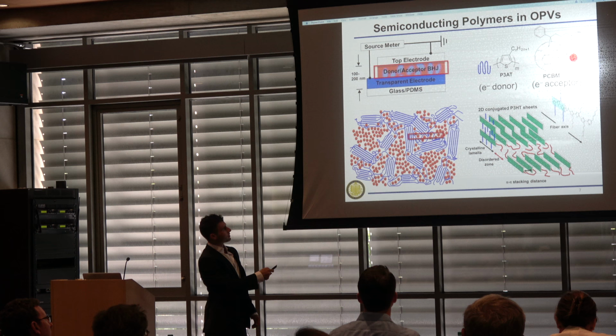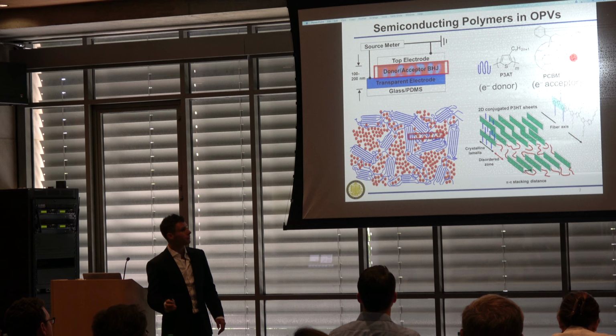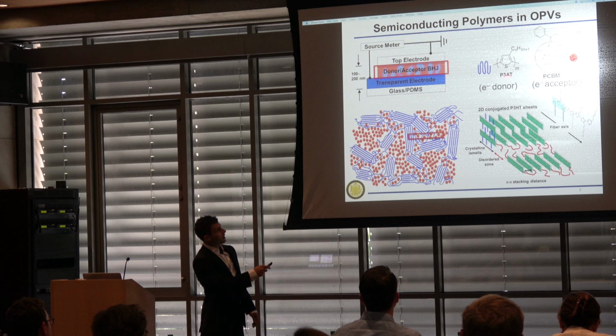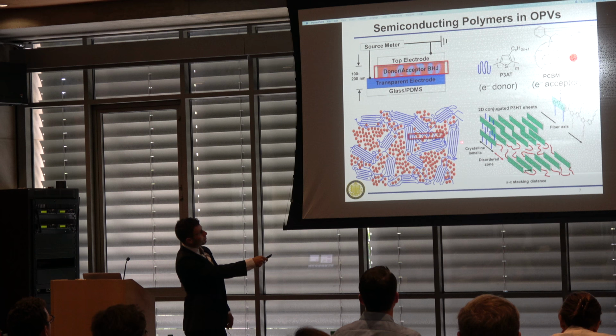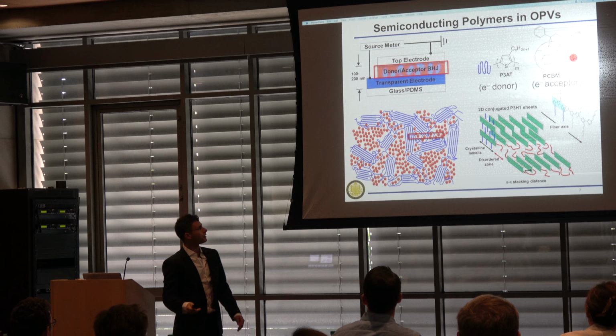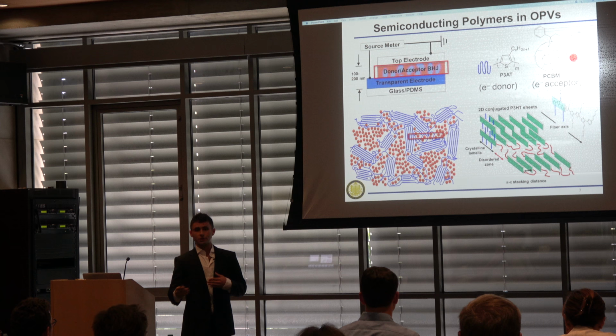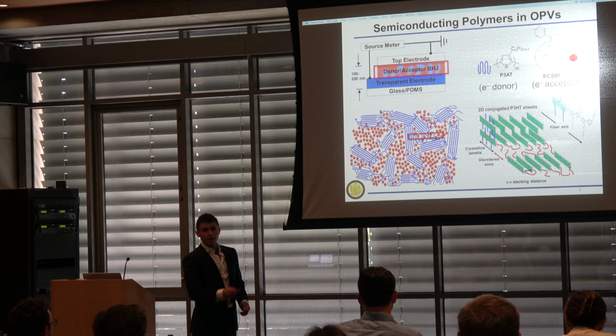So first crystalline phase, we'll look at the conjugated polymer, the P3AT. And because it's a very flat polymer, it has these thiophene rings, it will chain fold on itself. It will pi stack. And this creates these brittle but crystalline lamella structures. And they're mechanically much more brittle, but they're able to facilitate the mobility of charge very effectively. And then we have a second crystalline phase, and this is a pure PCBM phase. These spheres pack together very nicely.